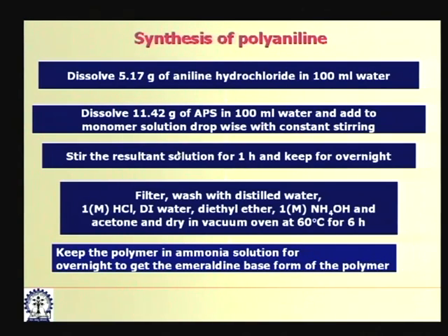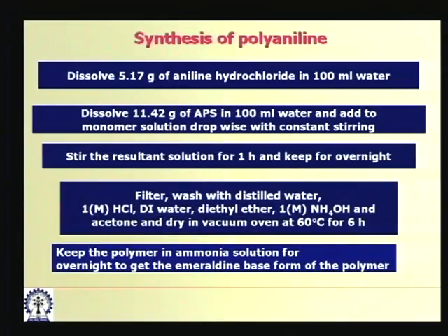Now, the small oligomeric intermediates which are formed during such polymerization, during such synthesis, need to be given scope for further growth, and for that reason the mixture is to be allowed to stand overnight under stirring condition. Okay.